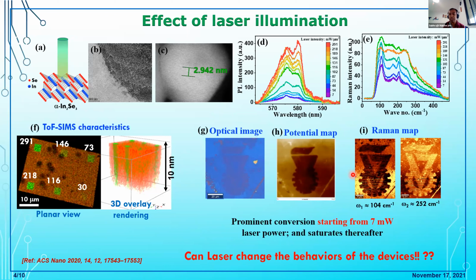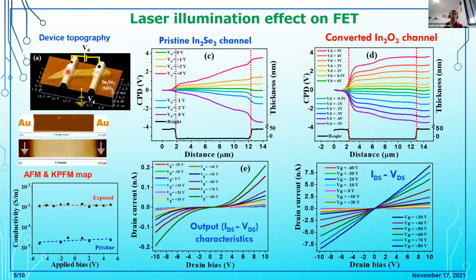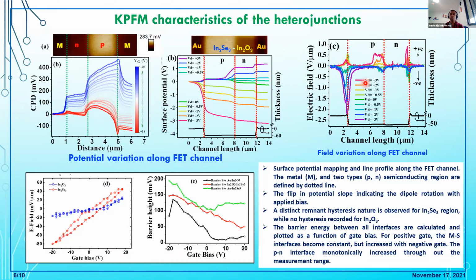So the next question is whether this irradiation can change the device property or not. For this, we fabricated a FET again and did the surface potential mapping as previously. And we see that the pristine indium selenide has this type of surface potential, but when the channel is converted to indium oxide, it changes the electrical conductivity.